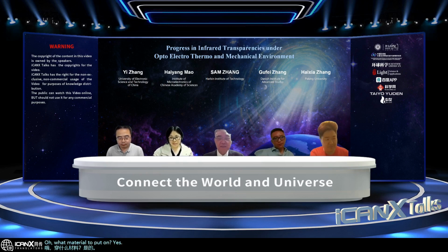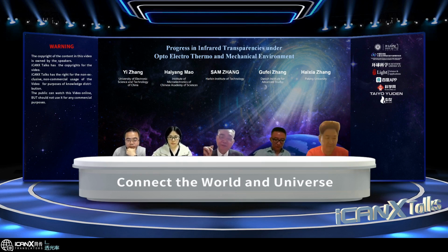Yes, this is going to be exciting. First of all, what we do is the simulation. We use theoretical calculation and input those materials data into the system and see first what material to put on each other, and then how thick each material is, because the thickness, as I mentioned, determines the transmittance. The thinner, the better in terms of transmission.